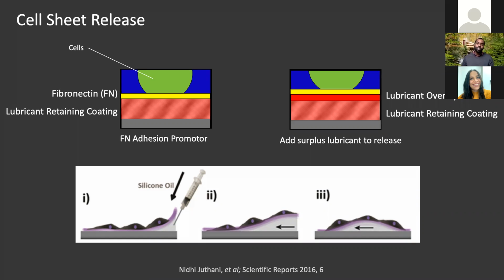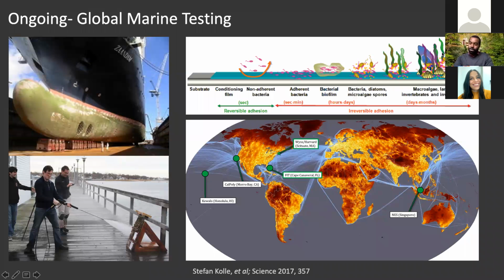So this is an interesting strategy, and again, going back into learning new strategies and learning how we can start to approach this. In the future, something that will be coming out in publications, we've been doing a lot of testing around the world with this silicone coating, this infused silicone coating, and trying to see, can it be turned into a marine coating? Can it be put on the bottom of ships to save energy through roughness, and also to reduce the amount or prevent toxic materials from being used in these coatings? That's what's typically used to just kill whatever sticks or whatever touches. So we're seeing really promising results. We had a publication in Science that showed when mussels stick to the surface, you essentially don't even have molecular signatures of the mussel adhesive on the surface. So very repellent surfaces.